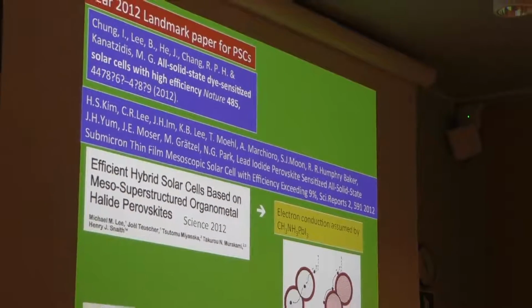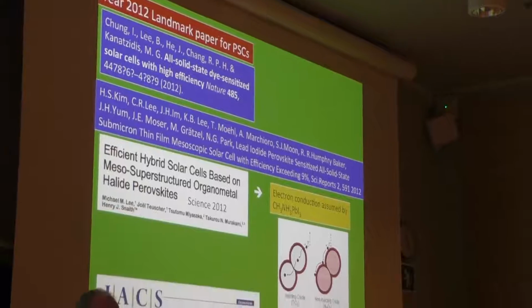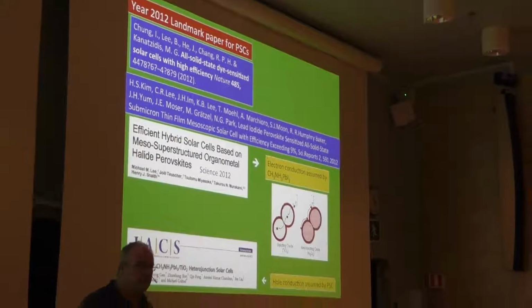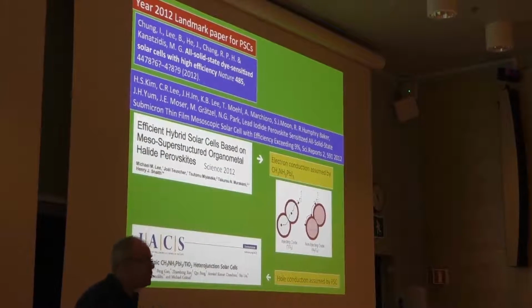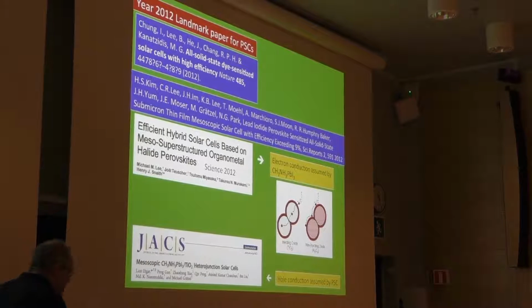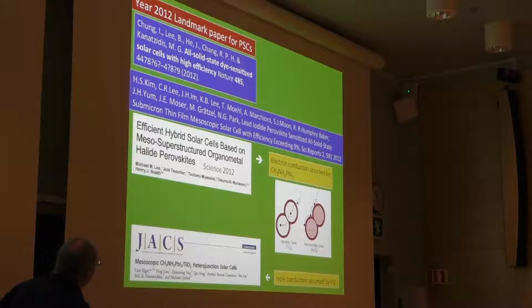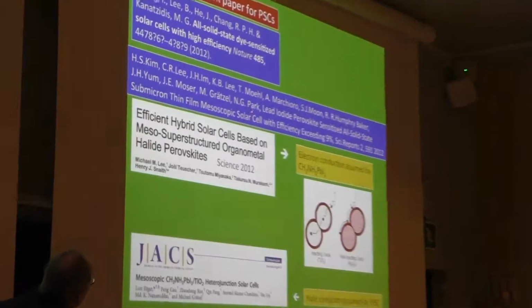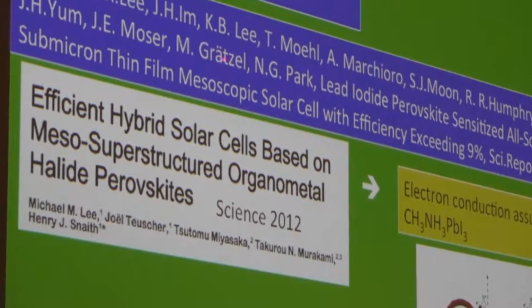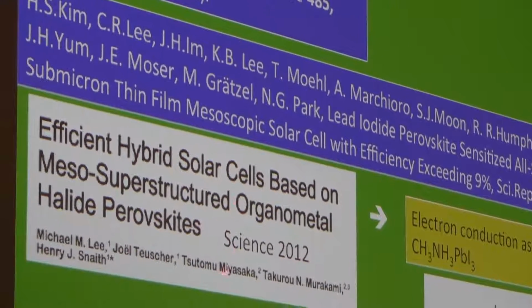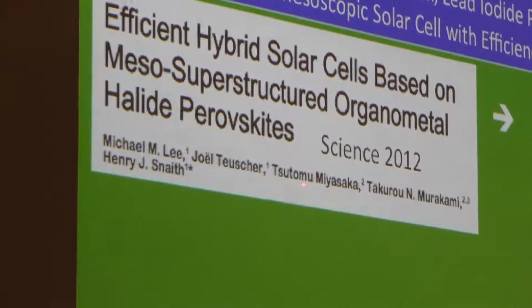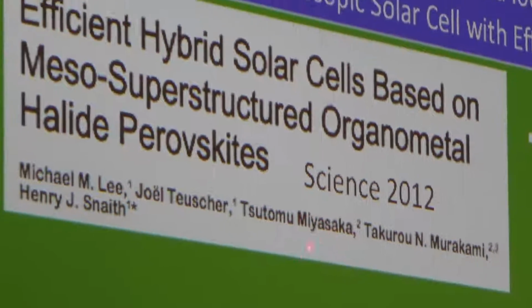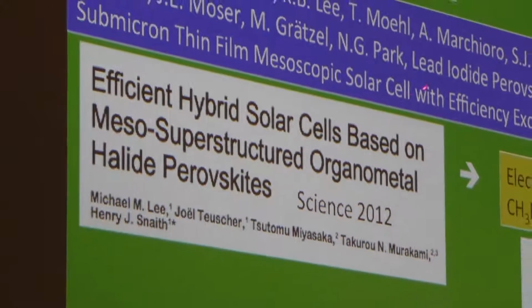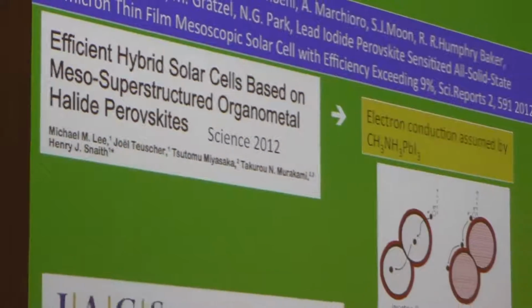and then the breakthrough really came in 2012, and what it was based on was that you replace the liquid iodide electrolyte with this Spiro solid state hole conductor. Then you avoided corrosion, and also the efficiency went up. So the breakthrough papers came from two independent works. It was Nam-Gyu Park in Korea who did this together with Michael Grätzel, and then Henry Snaith at Oxford took contact with Tom, and they published also very much the same result, about 10% efficiency, perovskite and Spiro, and so on.